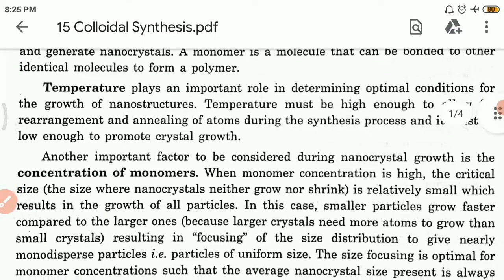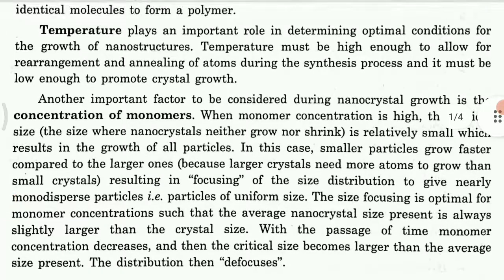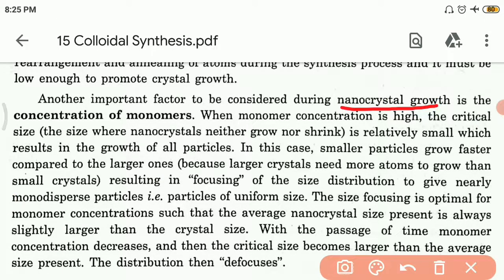Now the next important factor which is to be considered during the nanocrystal growth process is the concentration of the monomers. So when the monomer concentration is high, then the critical size, that is the size where the nanocrystals neither grow nor shrink, is relatively small, which results in the growth of all the particles, and in this case the smaller particles grow faster as compared to the larger ones. Why so? Because the larger crystals need more atoms to grow than the smaller ones. Okay, so this will result in focusing of the size distribution in order to give the nearly monodisperse particles, that is the particles which are uniform in size.